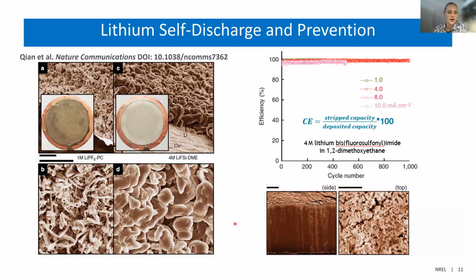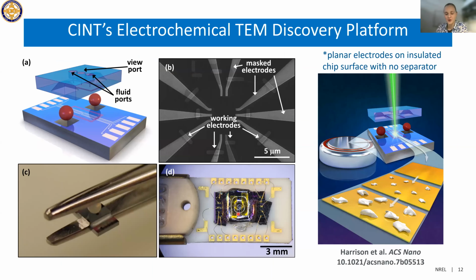And so here's showing the difference between cycling in 1 molar LiPF6 and propylene carbonate to what was shown here in 4 molar lithium FSI and dimethoxyethane. And so our group wanted to know what was the cause of this morphology difference. And so we put the electrolyte inside of our platform.